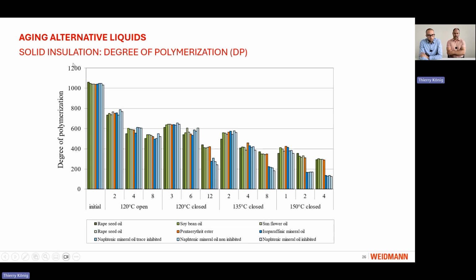Now we take a look at the solid insulation, what happens to the degree of polymerization in this experiment. The initial value was quite high, and then in all test vessels, we have a first decrease of the degree of polymerization. We can compare the 4 months in the open system to the 6 months in the closed system, and they're quite on the same level. But then in the closed system, we have a higher decrease of the degree of polymerization in the pressboard which is aged in mineral oil. This can also be seen in the 135 degrees closed system and in the 150 degrees closed system. This is also caused by the higher water content in the mineral oil.